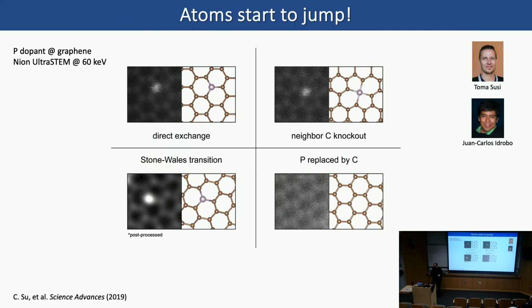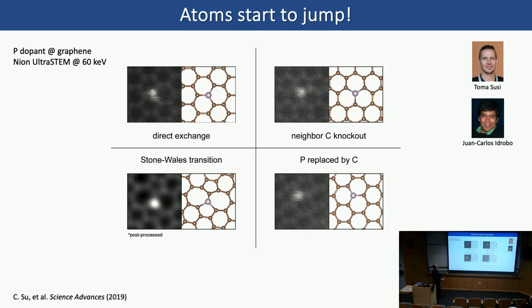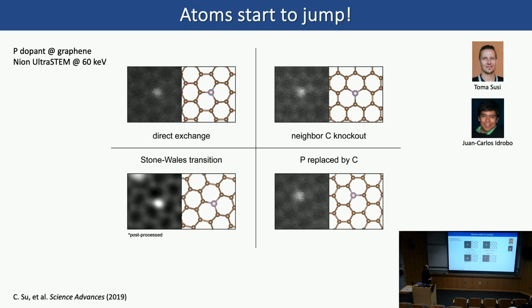When you put your sample into an STEM, because the electron has a very high acceleration voltage, it goes through the sample and transfers a certain amount of energy to the material. So it could potentially make some changes to the material. When it's uncontrollable, you could cause a lot of damage to the material. That's called electron beam irradiation damage.